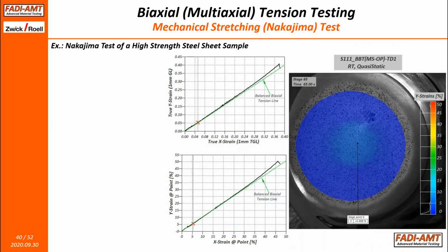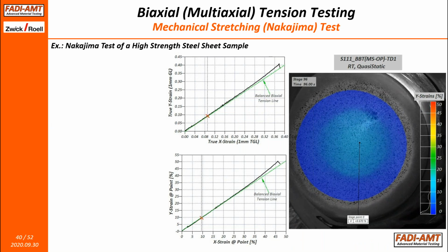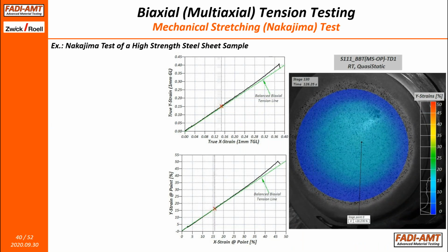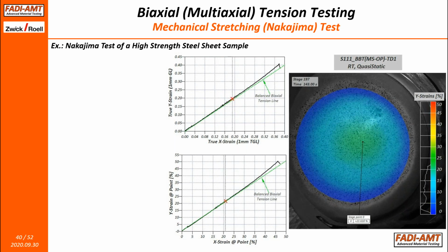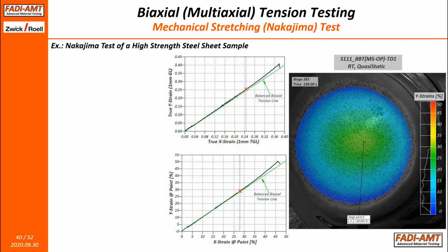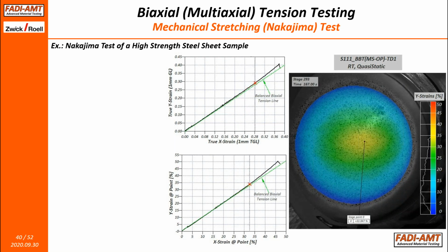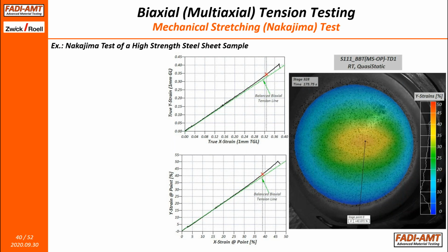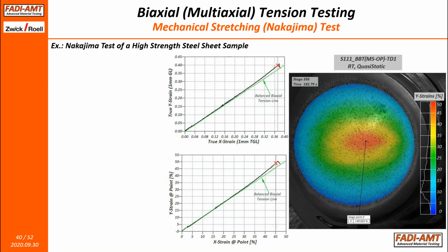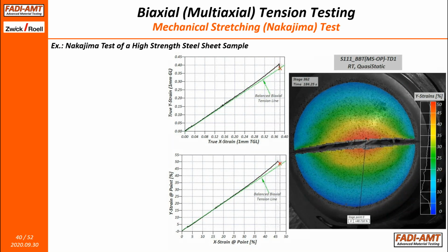So here's an example of a video done with DIC with a typical Nakajima test. Again, the nice thing about it with the use of DIC is that you can monitor the deformation of the sample. You can measure the axial ratio between the X and Y, and so you can determine whether it's balanced biaxial or not. In this case, it's almost perfect. And also you can see where the sample fractures exactly. So you can study closely the fracture of the material, if it's favorable or not.